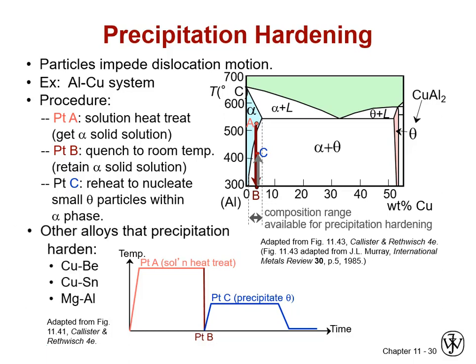This is called forming coherent precipitates, and it is the heart of the precipitation hardening process and what gives it its strength. Because the strain associated with all of those CuAl2 atoms on the edges, on their surface boundaries, not being exactly where they want, impedes dislocation movement, just like jamming a bunch of solid solution atoms in or straining the entire iron lattice in martensite.